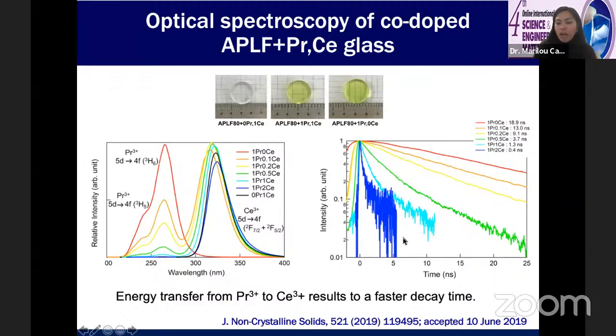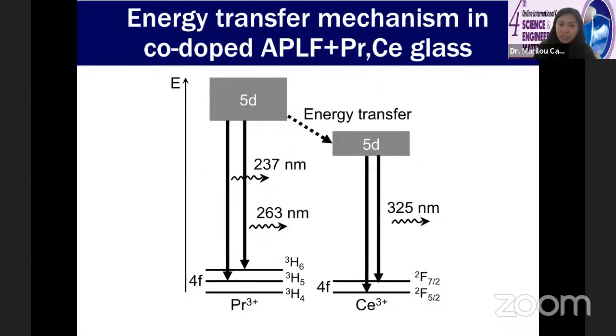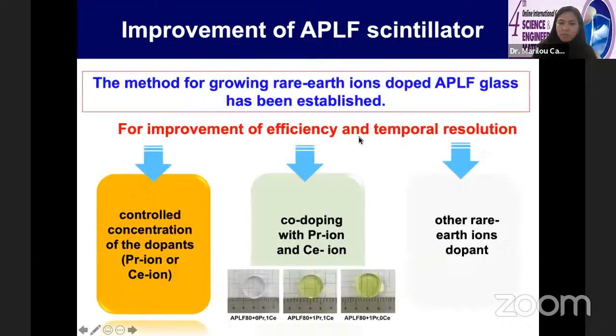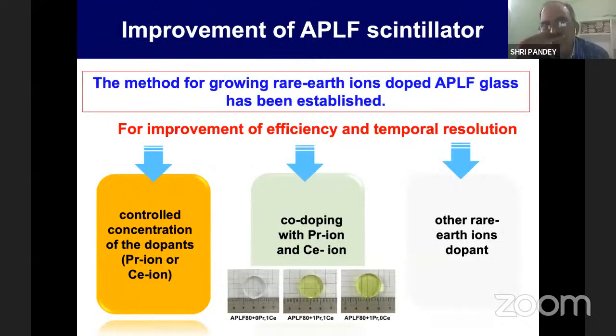By controlling how much cerium dopant is in our scintillator, we are able to control the luminescence decay time and therefore the response of our scintillator. And this graph just shows us the energy level diagram showing the energy transfer from praseodymium to cerium. Okay, so